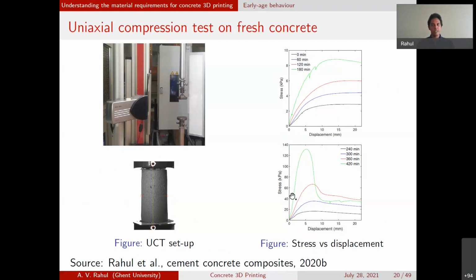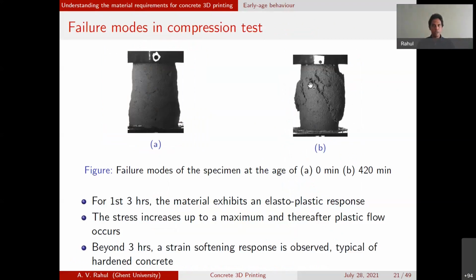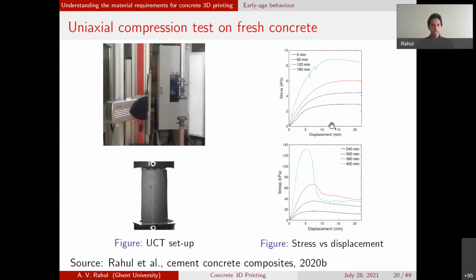But then as the material hardens, some rigid connections are formed, and the breaking of these rigid connections causes a shear crack formation, which more closely resembles what we see with hardened concrete. We see shear cracks forming, and then we see in the material response also, as the shear crack forms, a softening branch forming, which is again more typical with hardened concrete. So you see an evolution from an elastoplastic type material response to a strain softening type response, and this can be quite well captured from this test method.